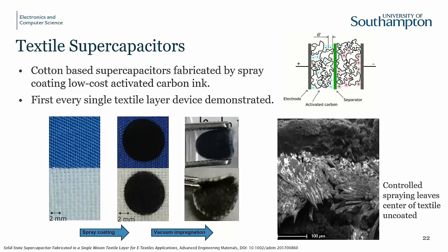Looking at storing that now, again, obviously we wanted to avoid batteries, so the obvious approach here was to look at supercapacitors. And fabrics, because of their porous nature, actually form a very good mechanical framework for making supercapacitor electrodes. So what we want to do is add a carbon material which has a very large effective surface area, and then add an electrolyte and make sure those two electrodes are separated and you can form a supercapacitor. This is how all supercapacitors are basically structured. We do this by making up a very low-cost carbon ink based on just activated carbon with a blend of carbon black to reduce the resistance a bit.